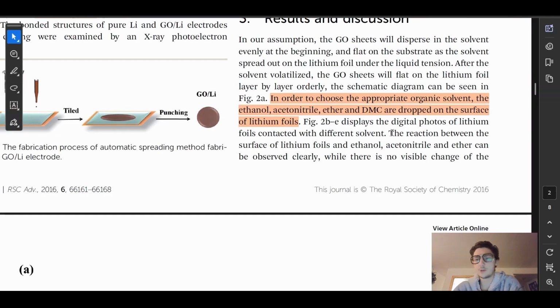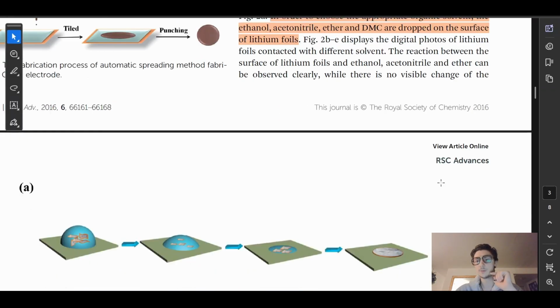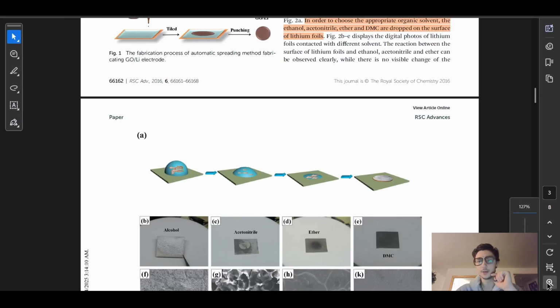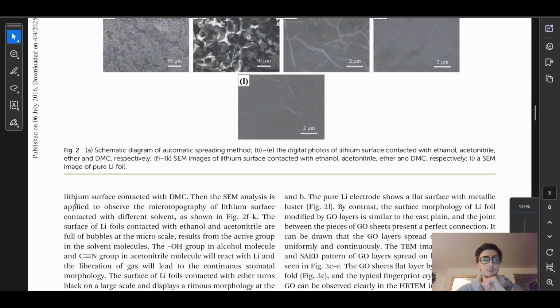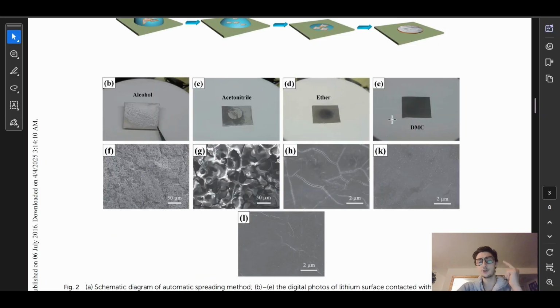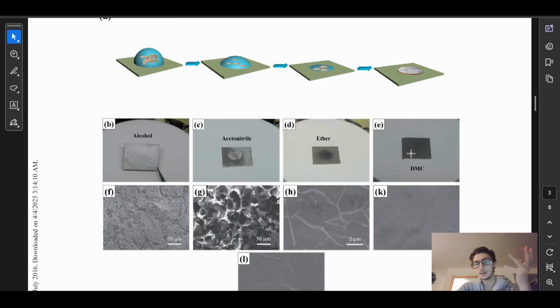B to E displays the digital photos of lithium foils contacted with different solvents, four different solvents. The reaction between the surface of the lithium foils and the ethanol, acetonitrile, and ether can be observed clearly, while there is no clear visible change of the lithium surface contacted with DMC. Okay, interesting, that is actually true. You put DMC on it, this looks exactly like the classic lithium. Here, you could see a dark spot in the middle. This is the ether. Here, you could see clearly some corrosion or some chemical reaction happened. Acetonitrile. Here, you could see the alcohol messed up the lithium, looks kind of icky. So all of these affected the lithium. This one looks completely unaffected.